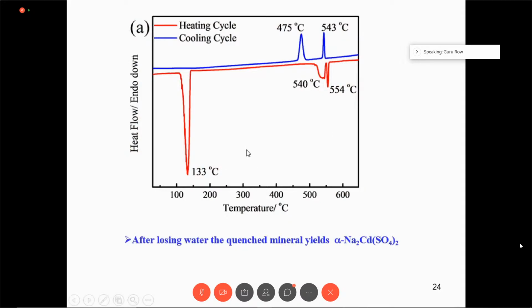Suppose we take the mineral and heat it up. When we heat it at 133 degrees, it loses the two water molecules. And at 540 degrees, as we saw, it undergoes a transition. And when we cool it back, it goes back to the so-called alpha phase. So the quenched mineral is definitely the alpha phase.